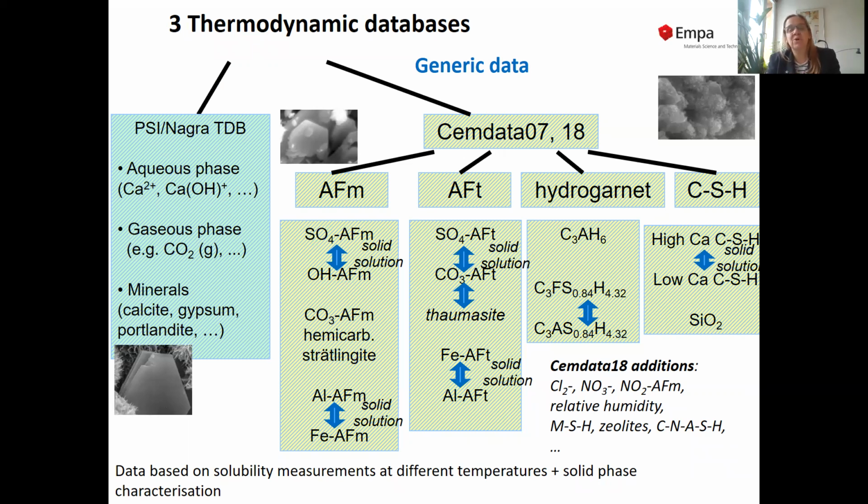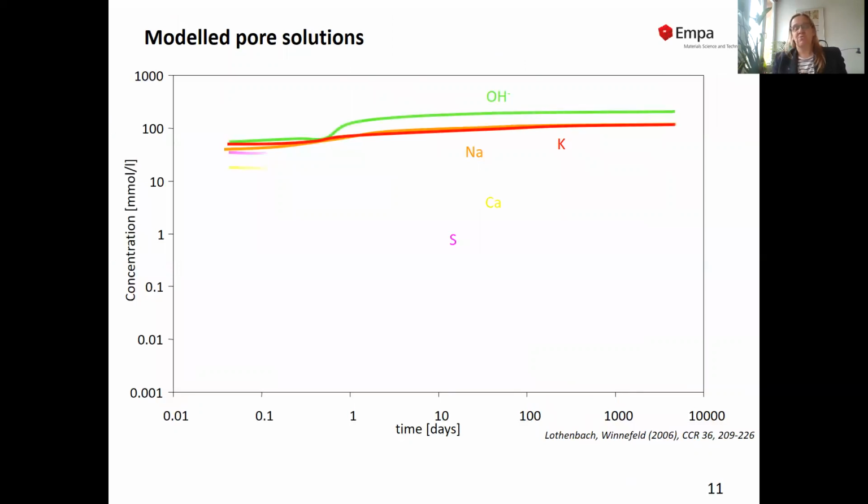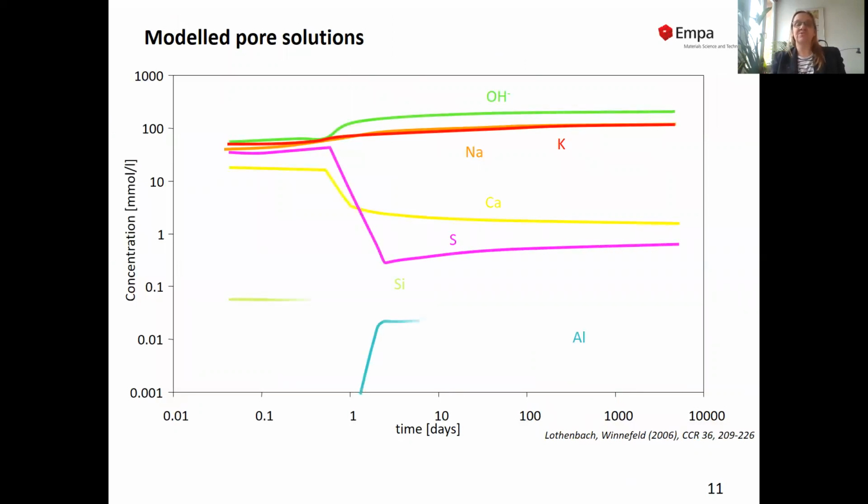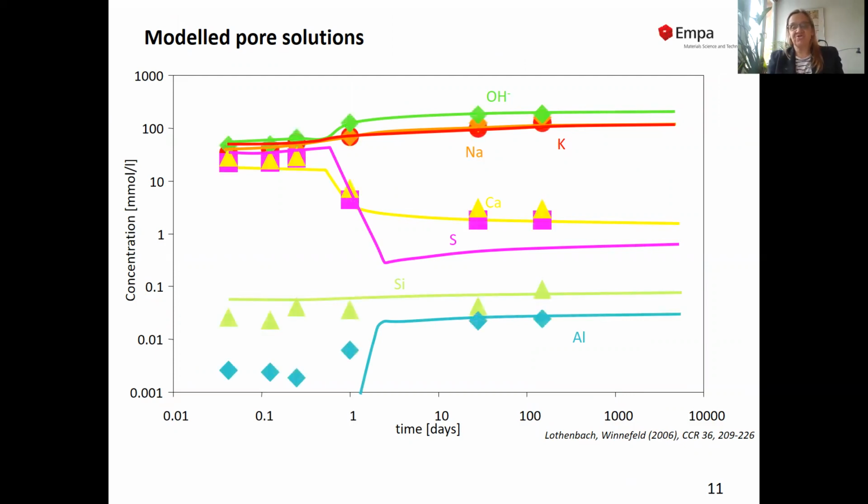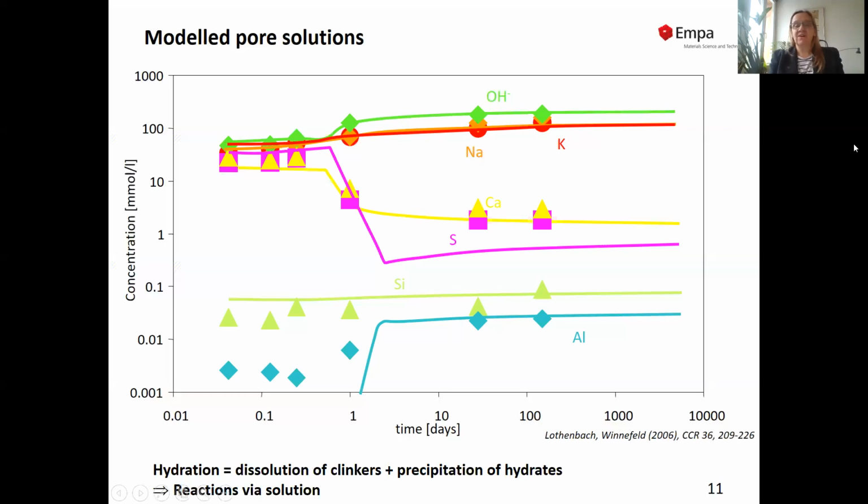This was basically the work of many PhD students who worked hard to get this data. If we now combine this kinetic equation with thermodynamic modeling, we can, for instance, predict the composition of the pore solution, as shown here, and compare it to the measured data. And one thing you can see, you have a nice agreement between the measured data and the calculated pore solution composition.